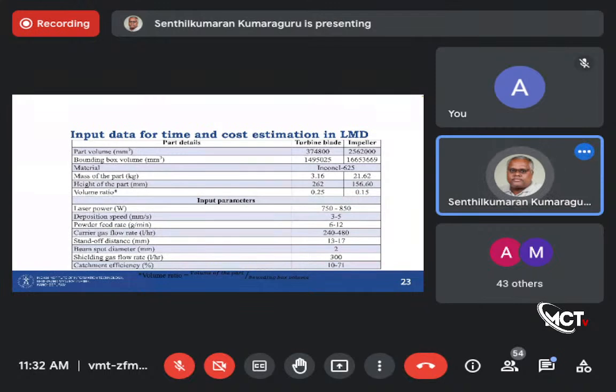So whatever material goes into that, divided by the total material supply, is given by the catchment ratio or catchment efficiency. That will depend upon the stand-off distance, and we assumed a very low value for some process parameters and a very high value for others. So you can just look at this. It varies largely from 10 to 71%. It depends upon many factors like the orientation of the surface with respect to the vertical direction, nozzle orientation, substrate orientation, so many factors. In fact, we have recently published a paper entirely on catchment efficiency, optimizing for thin wall deposition using LMD. That's a separate work. Maybe in some other talk we'll talk about it.